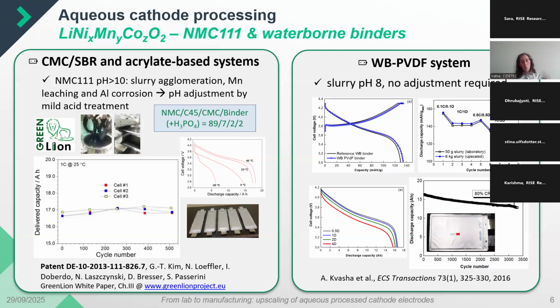The NMC 111 active material is not so susceptible to leaching, but this phosphoric acid was introduced at that time as this pH buffer and regulator.